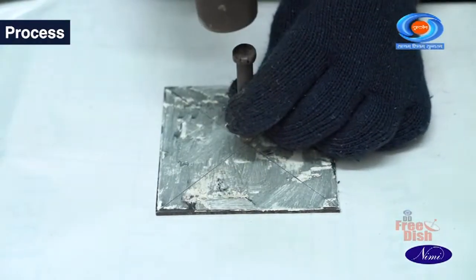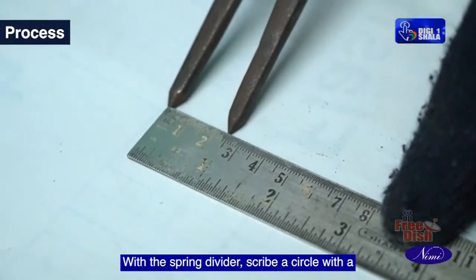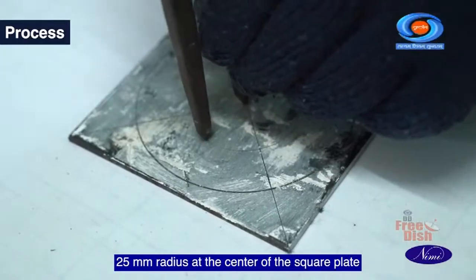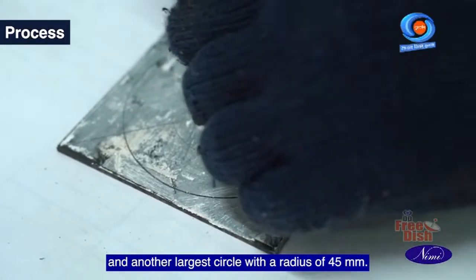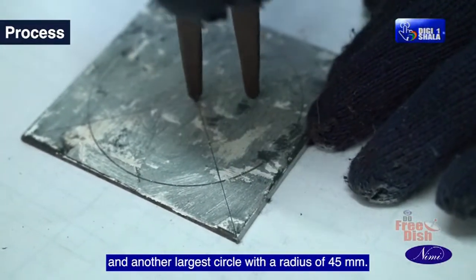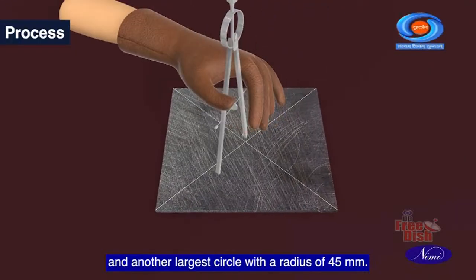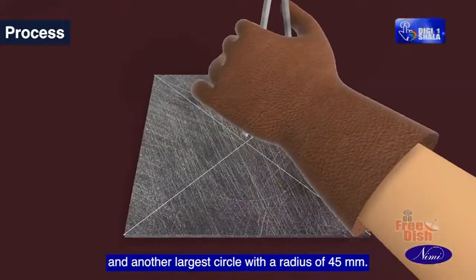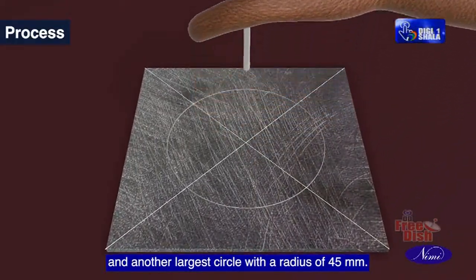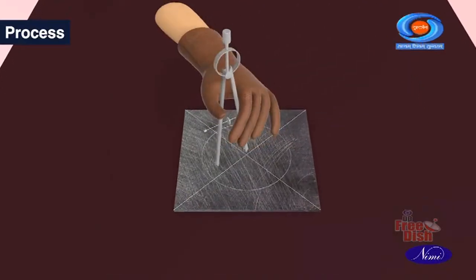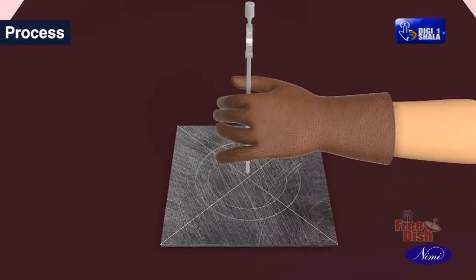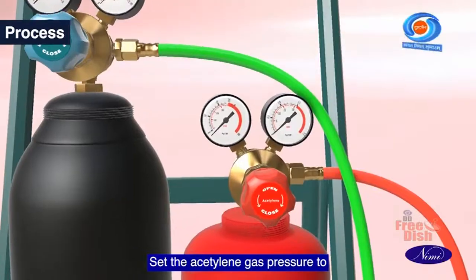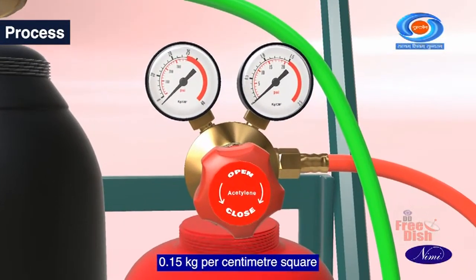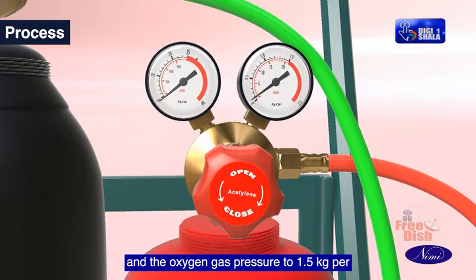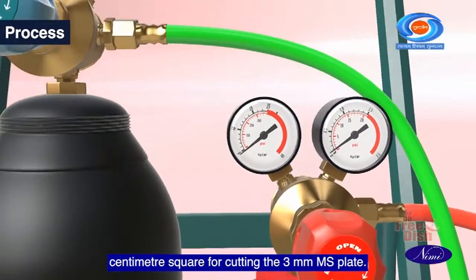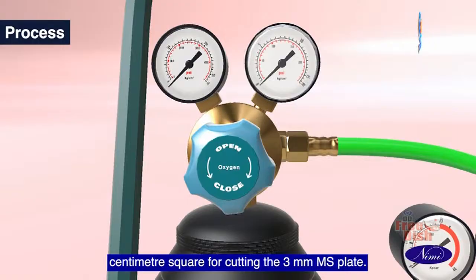Using a dot punch, with the spring divider, scribe a circle with a 25 mm radius at the center of the square plate and another larger circle with a radius of 45 mm. Set the acetylene gas pressure to 0.15 kg per centimeter square and the oxygen gas pressure to 1.5 kg per centimeter square for cutting the 3 mm MS plate.